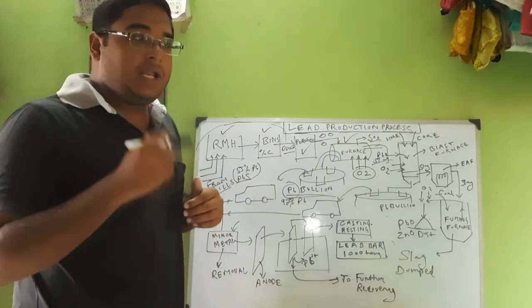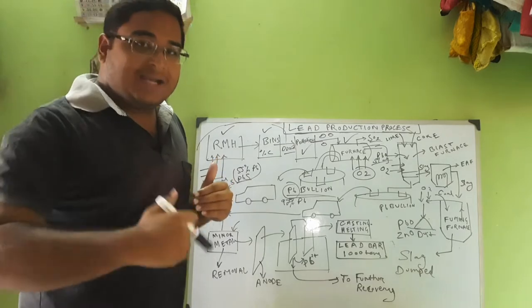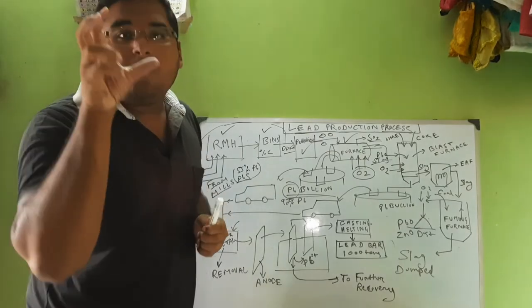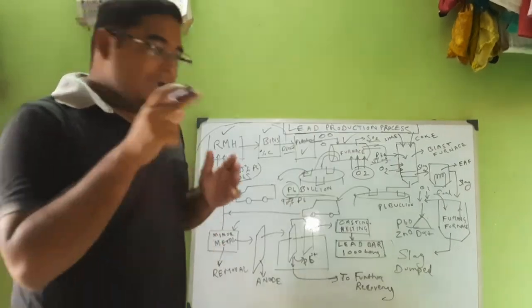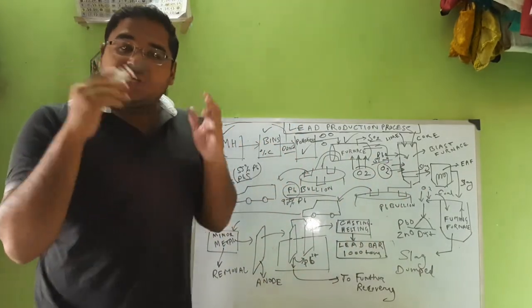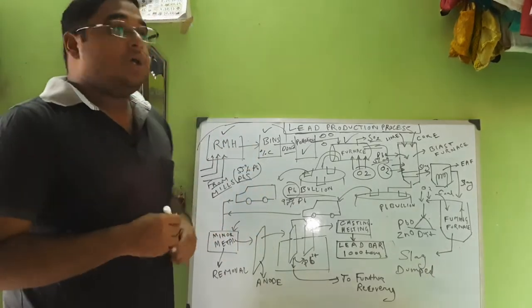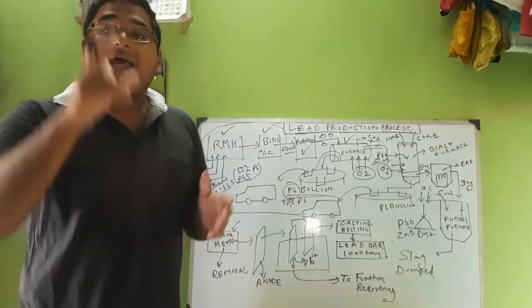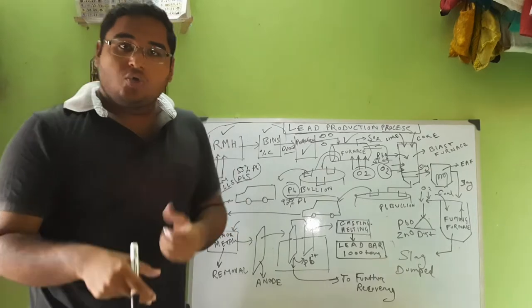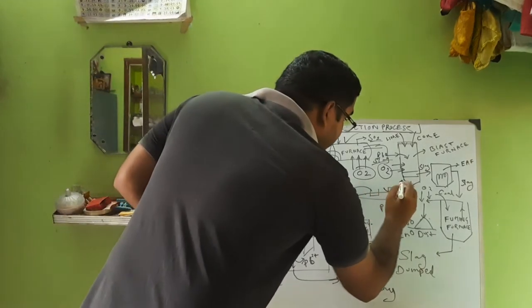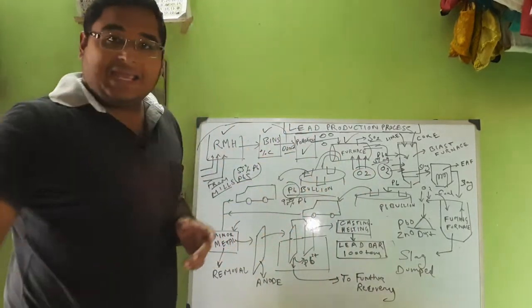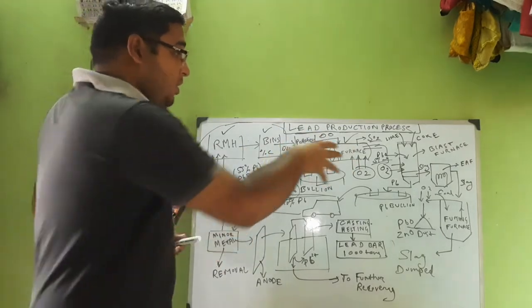Once PbO is free for reaction, coke — pure carbon — is fed. The reaction is: PbO + C → Pb + CO. Continuous supply of O₂ is given from side blowing, which combines with the CO to form CO₂. Carbon takes away the oxygen from PbO, forming CO, which is further converted to CO₂, and pure Pb is left. The Pb collects at the bottom and is again collected as lead bullion with 97–98% purity, then loaded onto trucks in solidified bullion form.